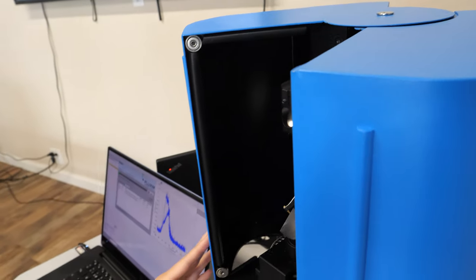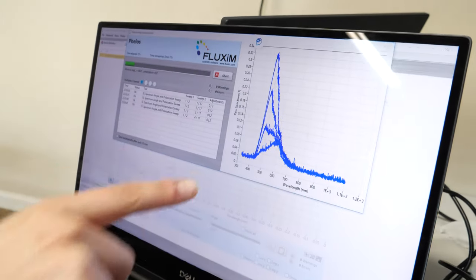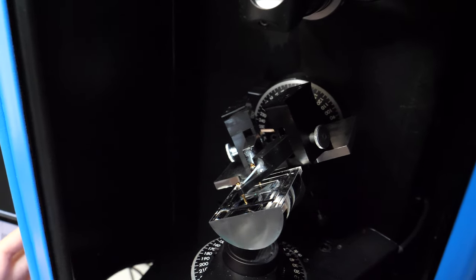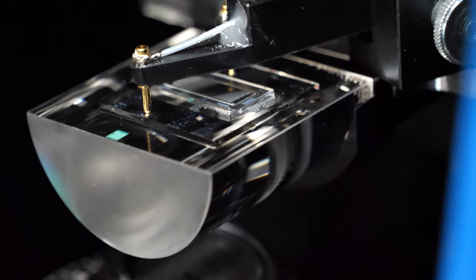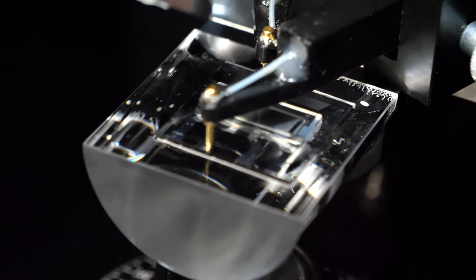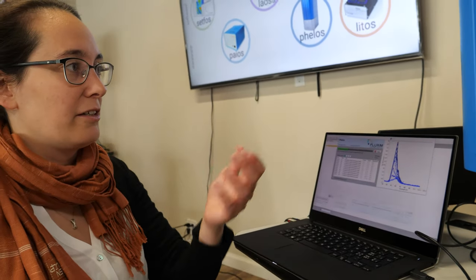Right now I'm performing an angular sweep — it's rotating and recording the spectrum for every angle. There's an OLED sample inside, and it is actually powered: two probe tips are connecting the cathode and anode, with 2.052 mA flowing through the OLED. The whole point is to see the angular dependence of the OLED emission.